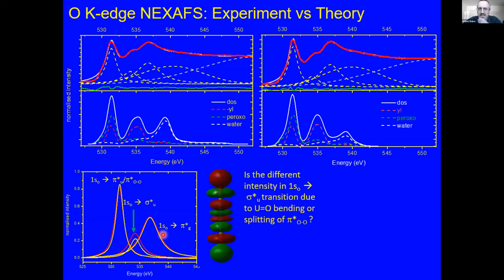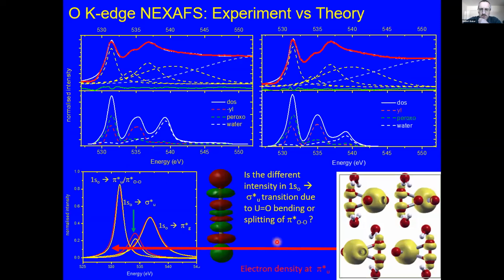And this has been a real challenge for theory. But eventually we were able to get pretty pictures because we're just simple coordination chemists, not theoreticians. And these are the density plots for this transition. And what you can actually see from this is that this is the sigma star molecular orbital from the peroxy with a uranium type orbital.